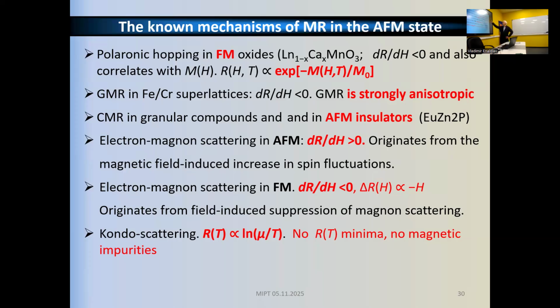Then even more famous is GMR in iron chromium superlattices, which produce exactly negative magnetic resistance, which is well tied to the magnetization. It's much stronger, maybe a factor of 10, but it's strongly anisotropic. When you apply current across or in plane, then you can either excite this effect or dampen it.